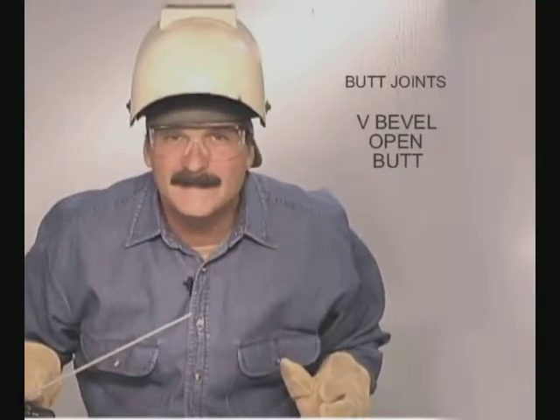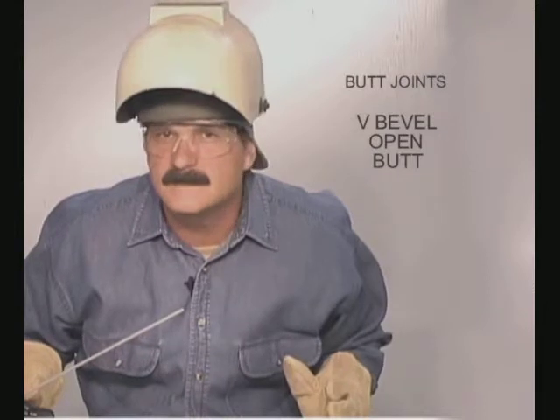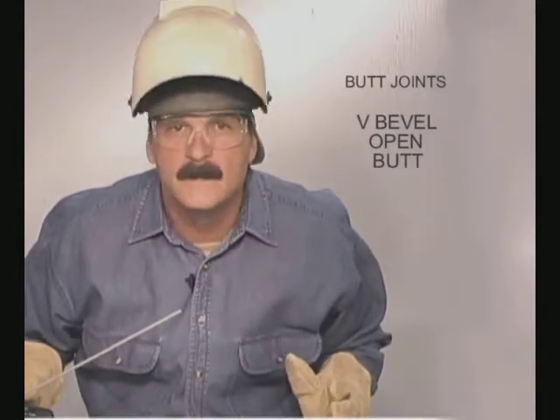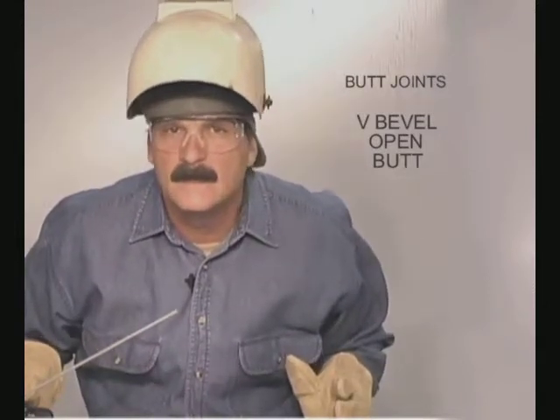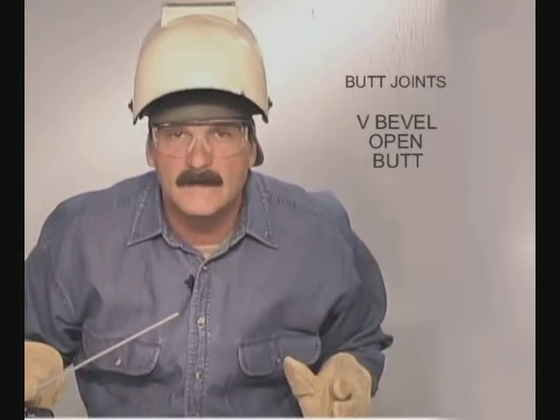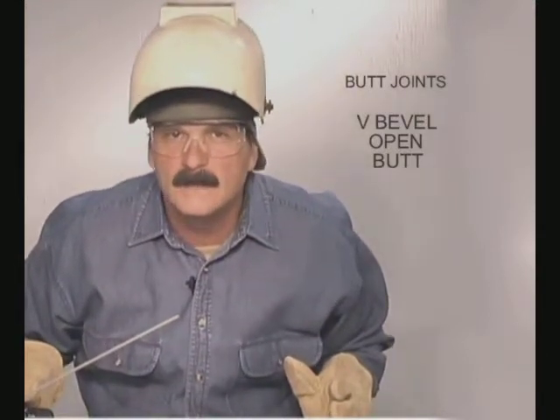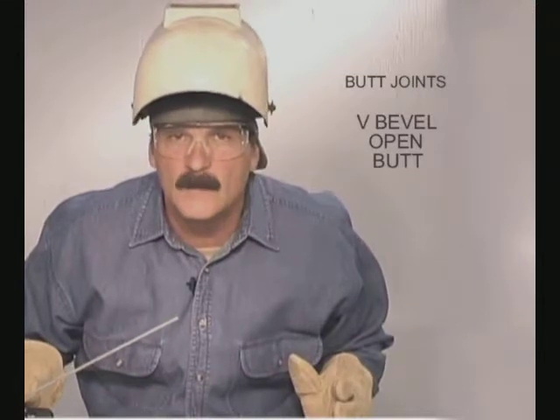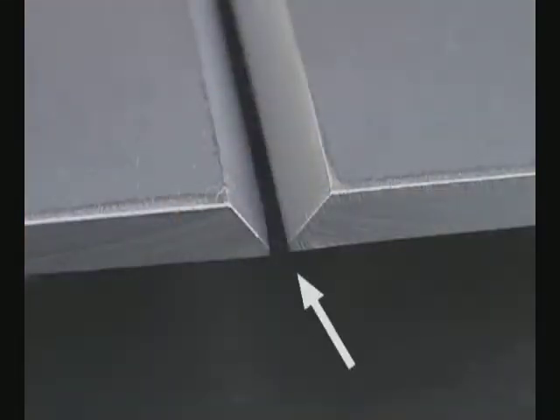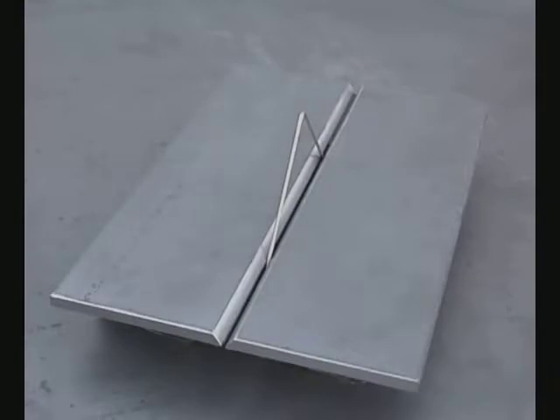With a 1/8 6010, I use a 1/16 oxyacetylene welding rod as a spacer with around a 16th landing. The size of the gap and landing can vary a little, but when you figure out what you like, try to keep it consistent for every weld you make. Line up the bottom edges of the metal. With a spacer to adjust the gap, run one tack, pushing the rod right down into the gap.